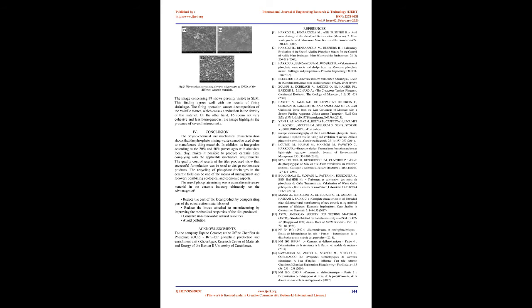Two types of shrinkage are evaluated: a mass shrinkage, a mass loss caused by the release of certain volatile components; and a diameter shrinkage, a loss in diameter caused by fusion of components, which tend to fill the voids existing between the particles. According to Table 4, only F5 has both considerably high mass and diameter loss.